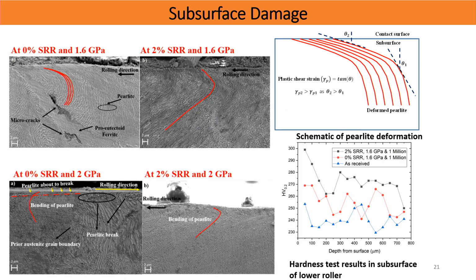And if you look at the subsurface, the image you are seeing in the center is before the test is run, and after the test is run, you see that the pearlite is bending, which I showed you before also. For very high slide to roll ratio, it starts cracking, and the cracks are created along this bending of the pearlite. And the hardness also changes because of this, because ratcheting is happening. So the hardness at the surface also changes. We measured that it changes by about 20%.